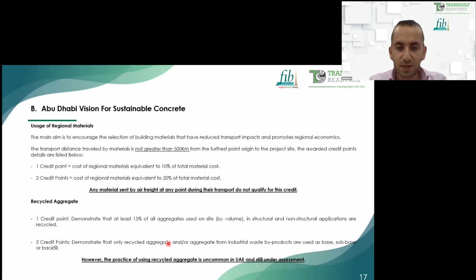Moreover, the use of recycled aggregate. We will get 1 additional credit point in case 15% of all aggregate used on site by volume in structural and non-structural applications are recycled, and 2 credit points if it is demonstrated that only recycled aggregates from industrial waste byproducts are used as base, sub-base, or backfill. However, the practice of using recycled aggregate is uncommon in UAE and still under assessment.